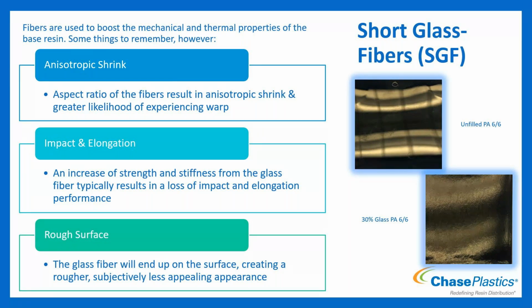And because of that, they tend to line up when they're flowing into your part. When they line up - think logs going down a river - they tend to line up. So as they line up, when the part goes to shrink, all of the fibers that are lined up in the flow direction are going to inhibit some of that shrinkage. So you're going to get less shrink in the flow direction than you will in the cross flow direction. So that's how you end up with non-uniform, or anisotropic, shrink.